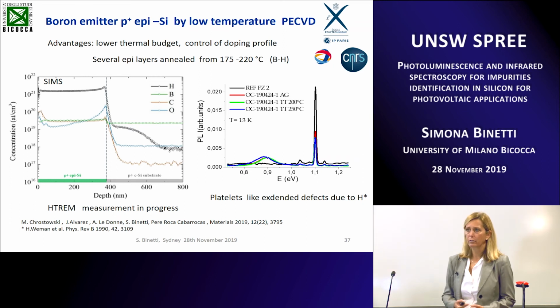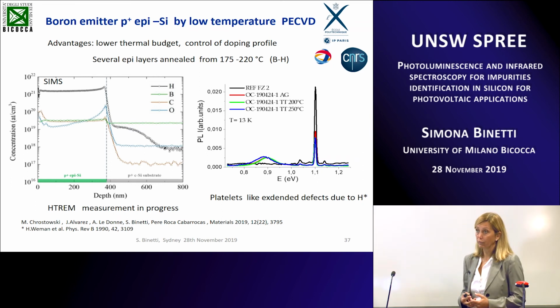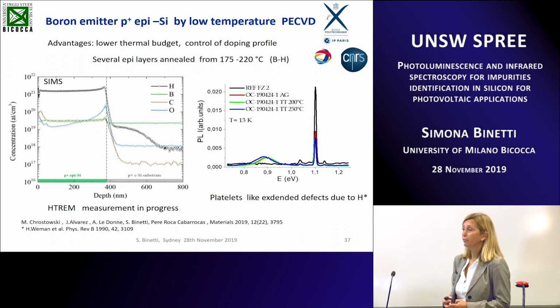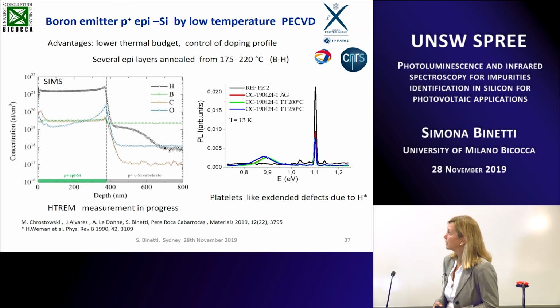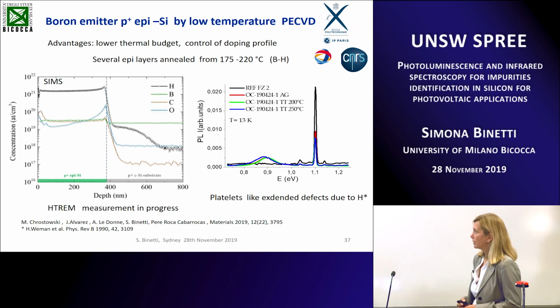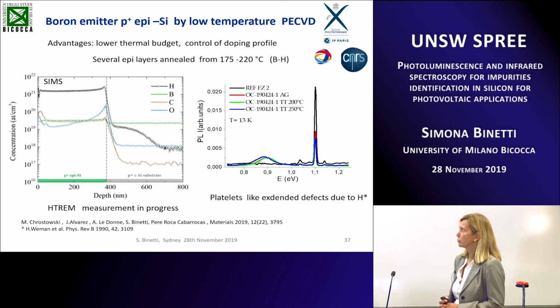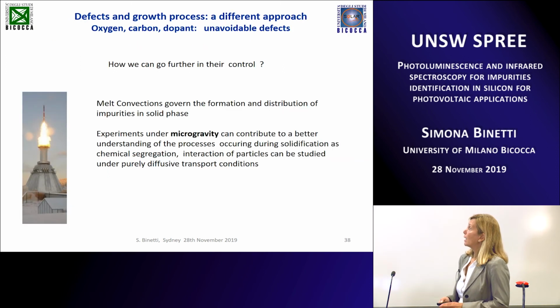When you have a very high concentration of hydrogen, you have precipitation of hydrogen, and you can form the so-called platelet-like defects that can be seen also by TEM measurement. We have some evidence about that, but as we didn't publish yet, I cannot show the transmission electron microscopy, but we have seen that there is a good correlation between this band and the presence of this extended defect.